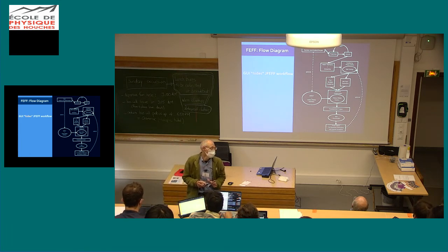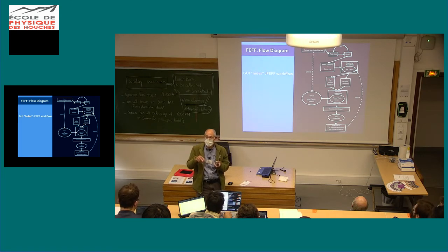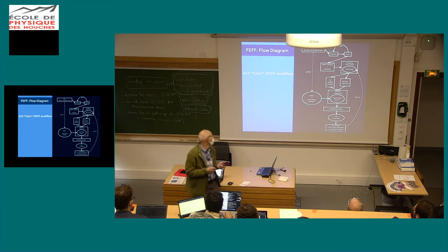So for the multiple scattering path expansion, each path has a given length, and we do a Debye model by fluctuating the total distance along that path. So each path has its own Debye-Waller factor. You have to specify the Debye temperature and the temperature in order to do that, which will be on the GUI, but I'll come to that later.